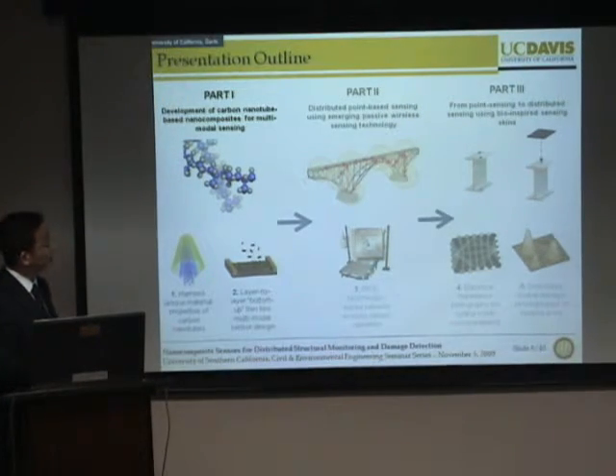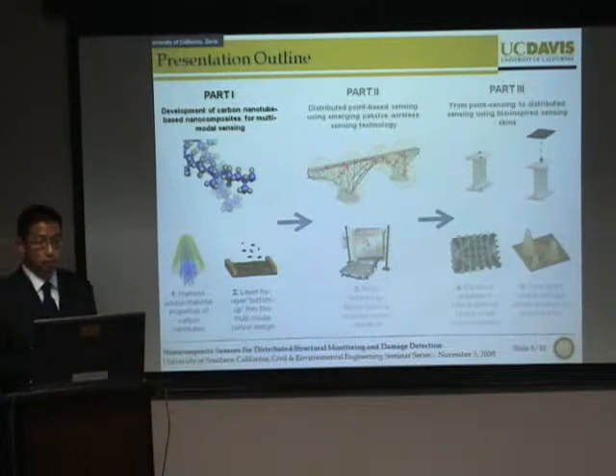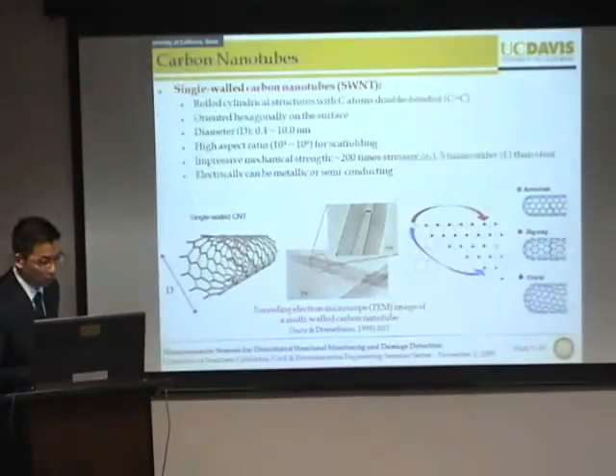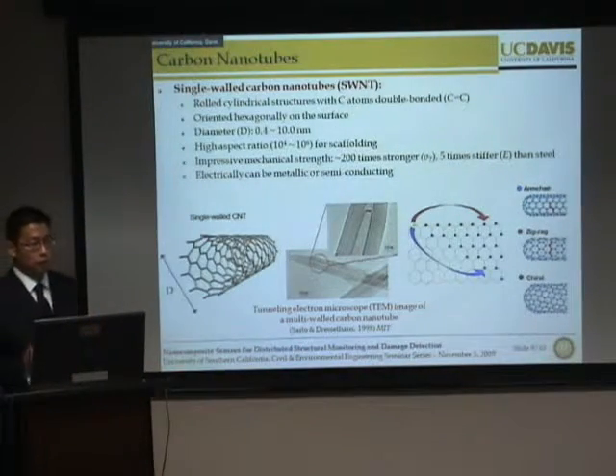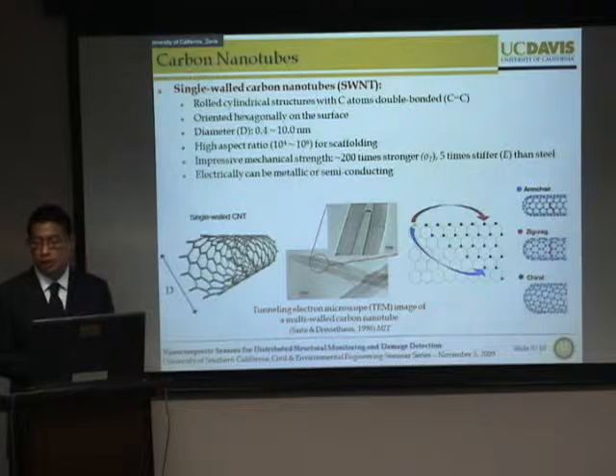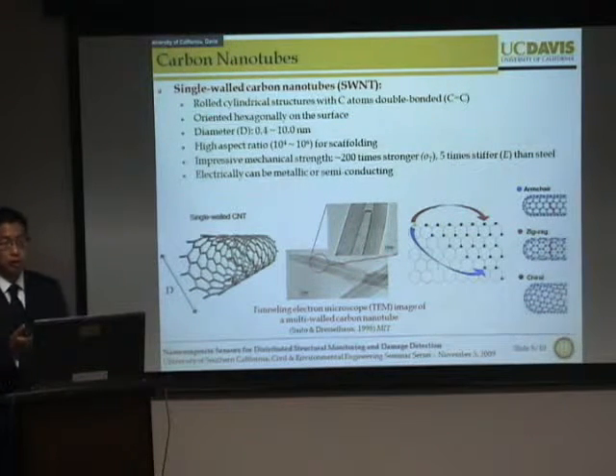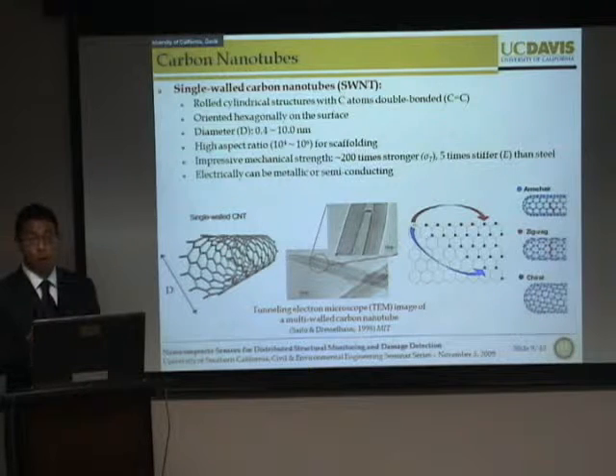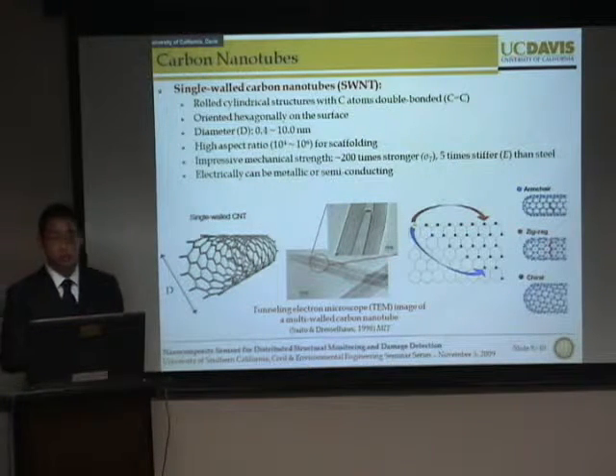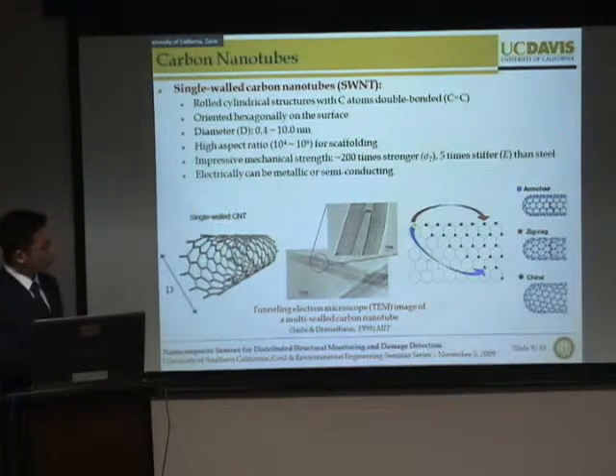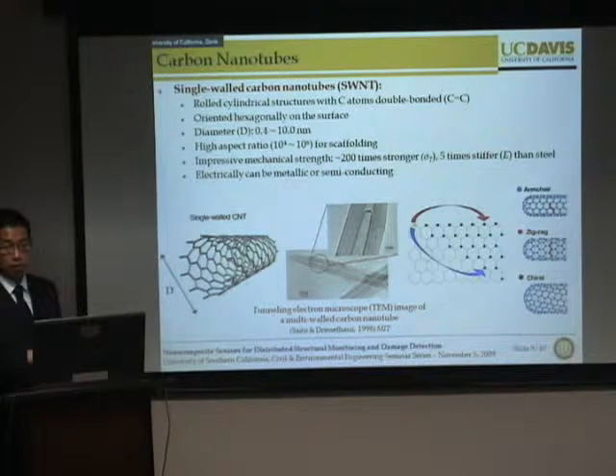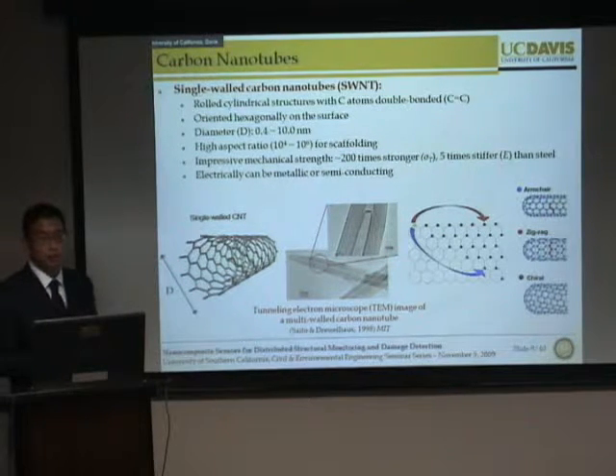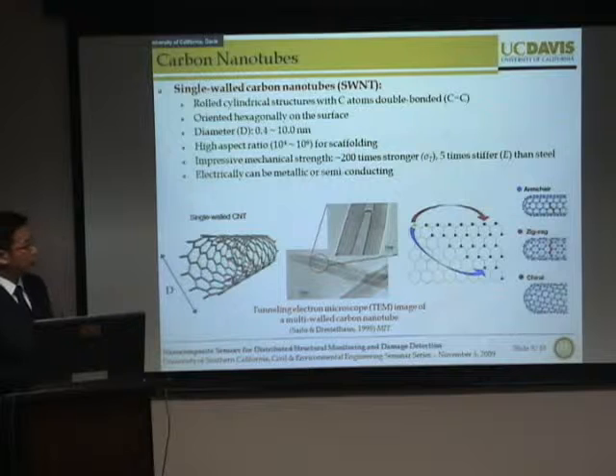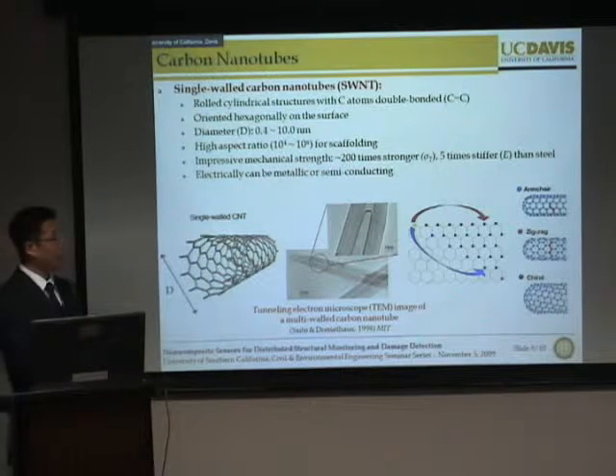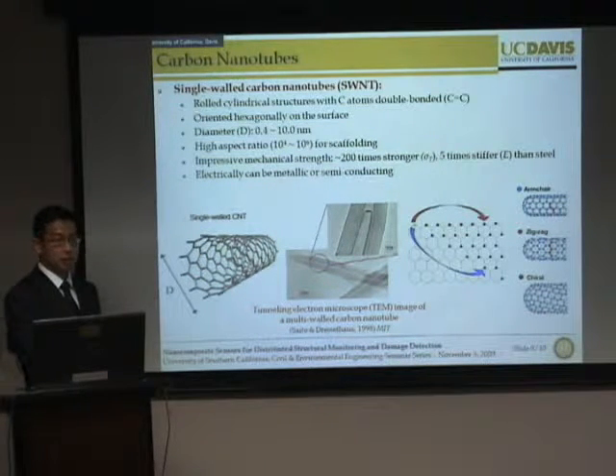So first, the development of carbon nanotube-based nanocomposites for multimodal sensing. Now, the material of choice that we've employed are carbon nanotubes. And in case you don't know what a carbon nanotube is, its physical structure is simply a graphite sheet or a graphene sheet that's rolled to form this cylindrical structure. Its physical structure is characterized by a diameter of approximately 0.4 to 10 nanometers. But what's most impressive and unique about this material is its incredibly high aspect ratio. That is its long length.